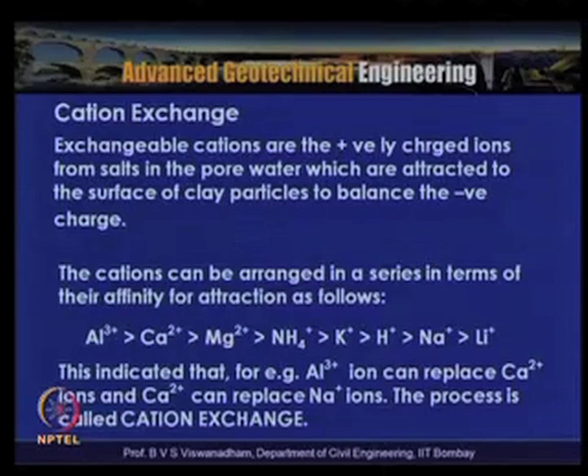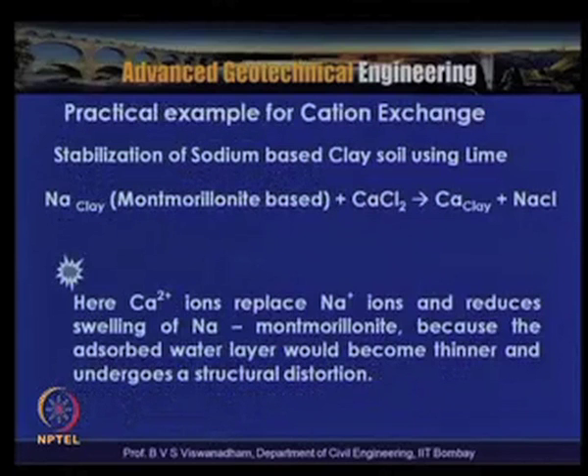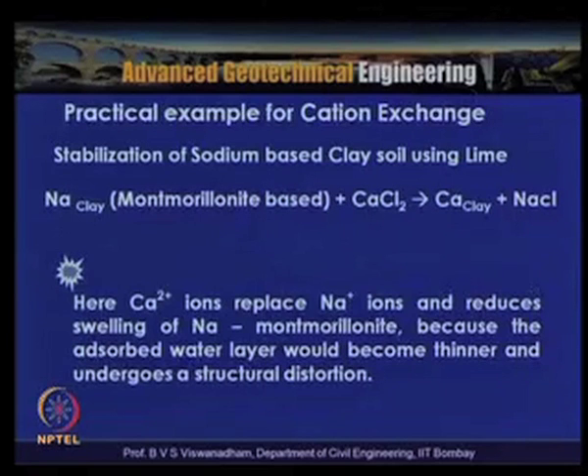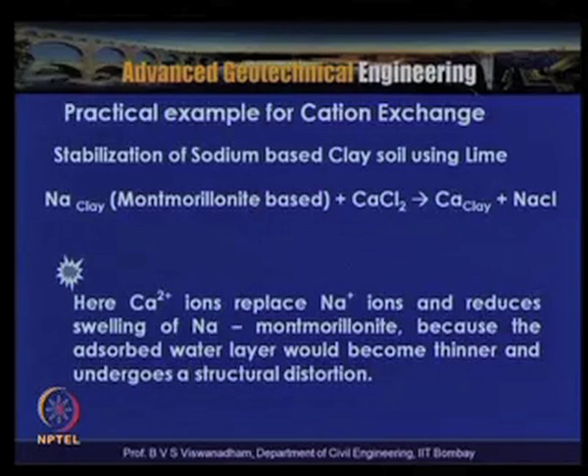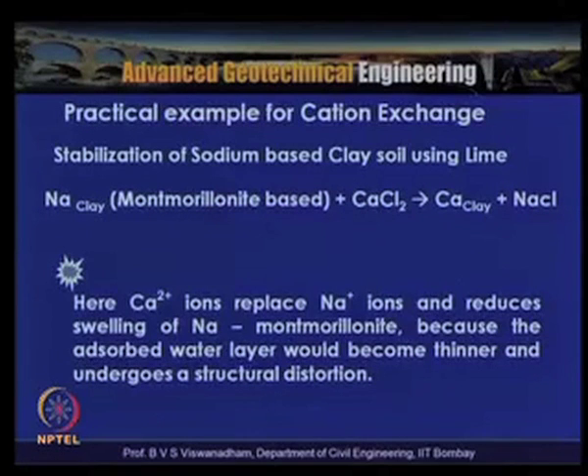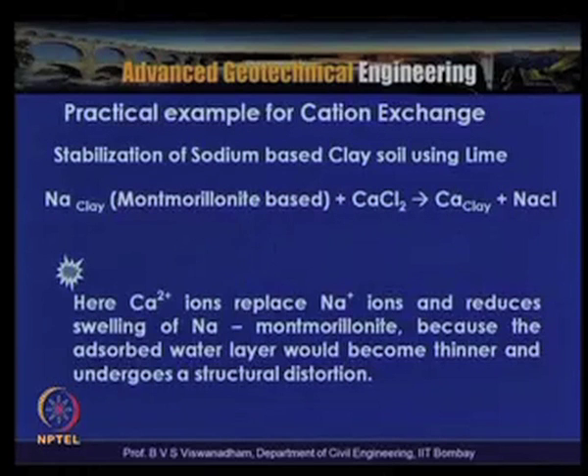A practical application of cation exchange is the stabilisation of sodium-based clay using lime. When sodium montmorillonite clay is treated with calcium chloride, calcium clay and sodium chloride are formed. The Ca²⁺ ions replace Na⁺ ions, reducing swelling of sodium montmorillonite. This causes the adsorbed water layer to become thinner and undergo structural distortion, decreasing the affinity for water — the basis of lime stabilisation used in practice for montmorillonite-bearing soils.